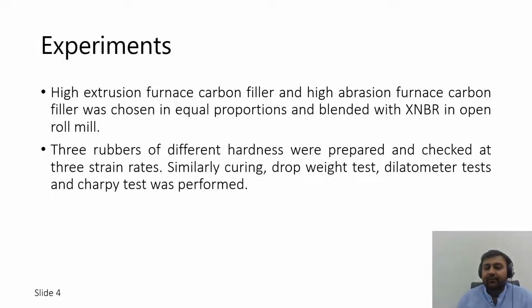And we performed tensile test at three different strain rates, as you know that rubber is viscoelastic in nature. And similarly, we performed curing test, drop weight test, dilatometer test, and Charpy test for mechanical characterization.